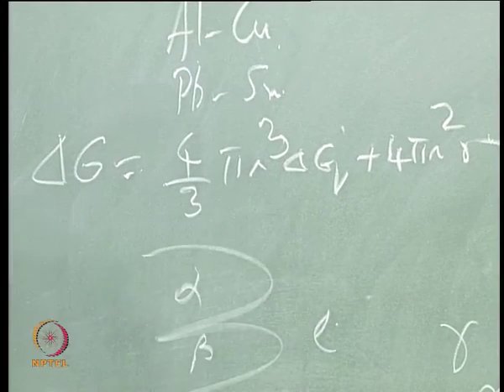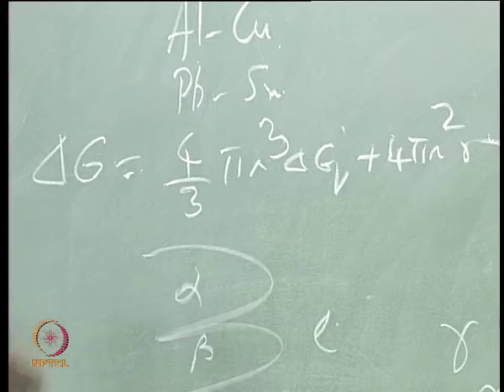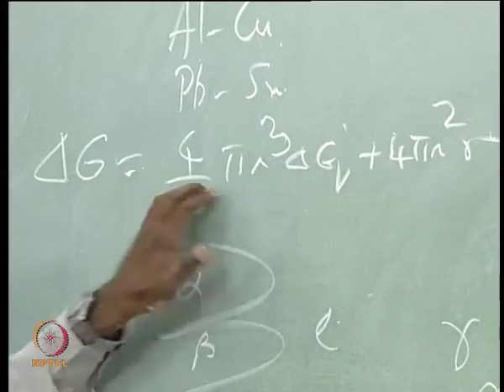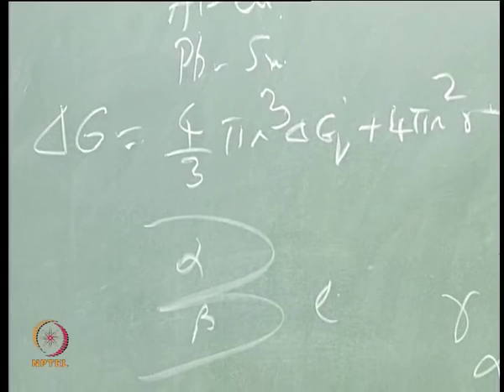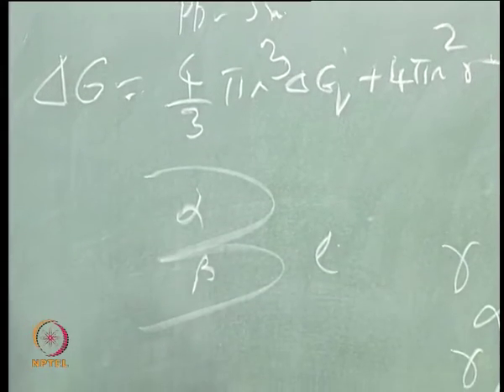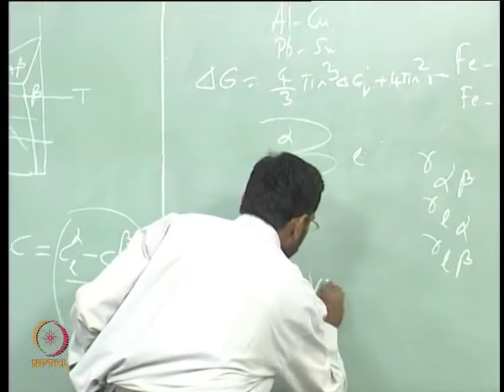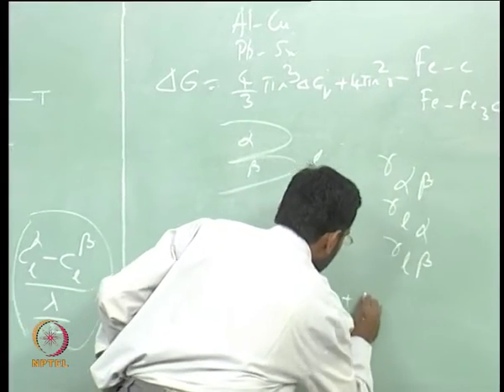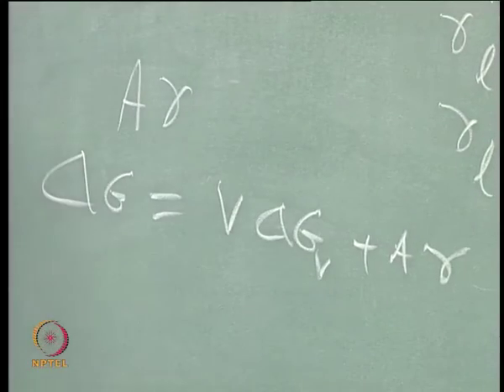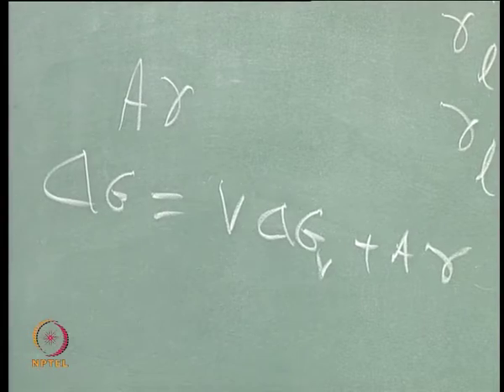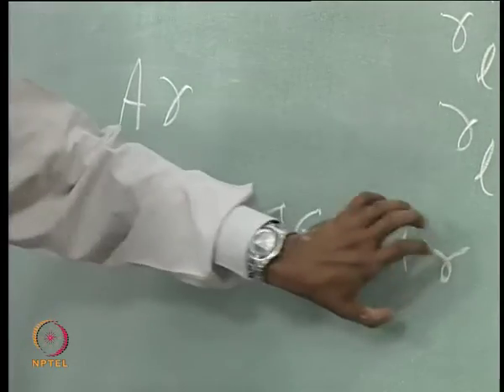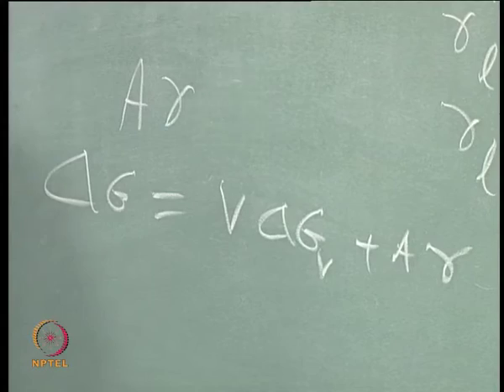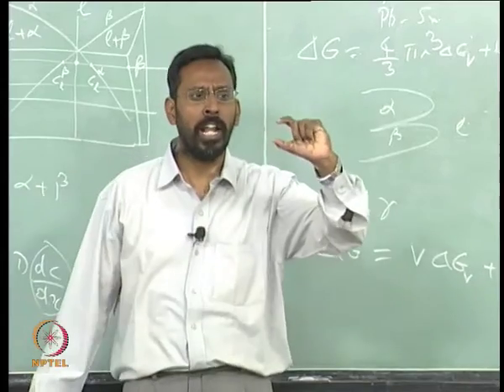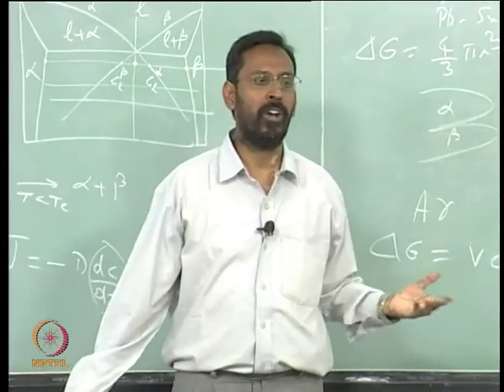Of course there we have assumed a spherical nucleus, we are not talking about eutectics there, but if you talk about eutectics, the same thing holds good, except that these geometric factors will change. Basically, I can write delta G as V into delta GV plus A into gamma, am I right? So it is this A into gamma that needs to be minimized, so that even at a smaller undercooling the liquid can become a solid.